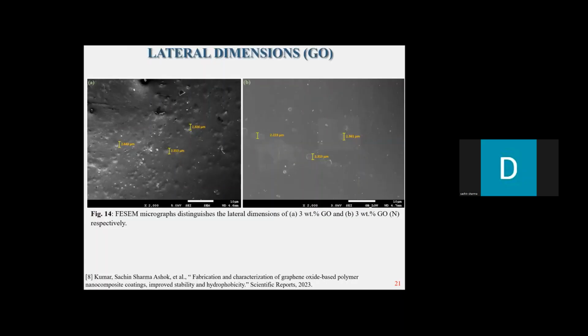So one important thing that I did as another step to verify the results was to calculate the lateral dimensions of the GO. So I took the highest loading, the highest concentration among all the samples, which was the 3 weight percentage GO. For figure A, it illustrates the sample that was prepared without the influence of vacuum. And B was the one with the influence of vacuum. And we could see that without the influence of vacuum, larger lateral dimensions were exhibited compared to B, which was slightly smaller. And this confirmed that the influence of vacuum plays a key role during the fabrication process of the graphene oxide.